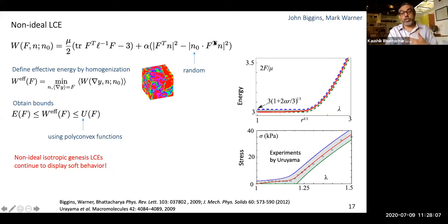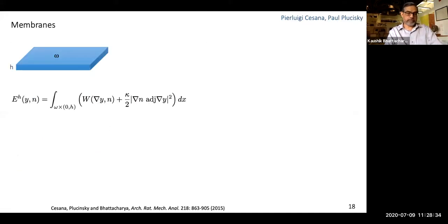And so by doing the simple bounds, you can understand that even if you don't have ideality, that is, you have a non-ideal material, polydomain with lots of these fluctuations, you can still retain this soft behavior. And that makes these materials much more attractive for application, because now you don't have to go through this very complicated process by which you try to get rid of this term. So that's a use of theory to try and motivate a new way of making these materials.